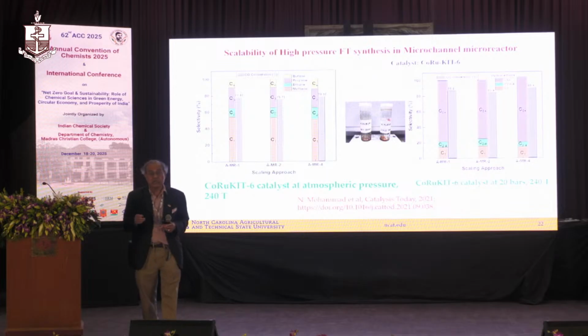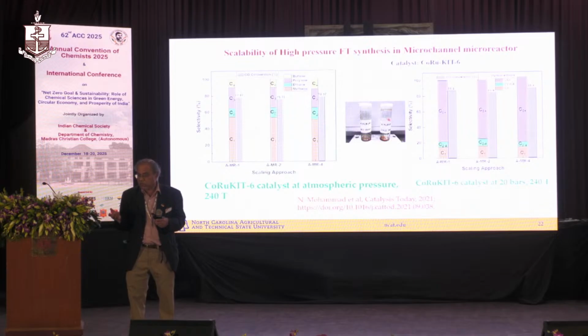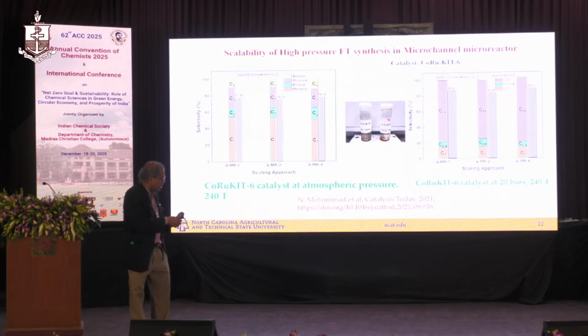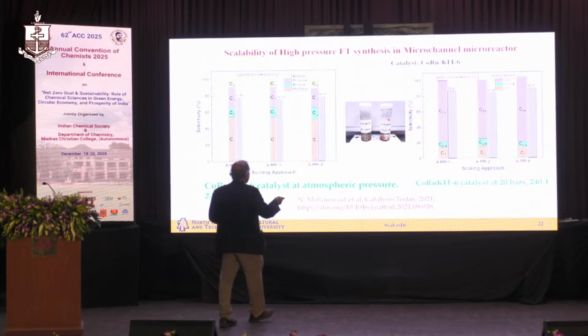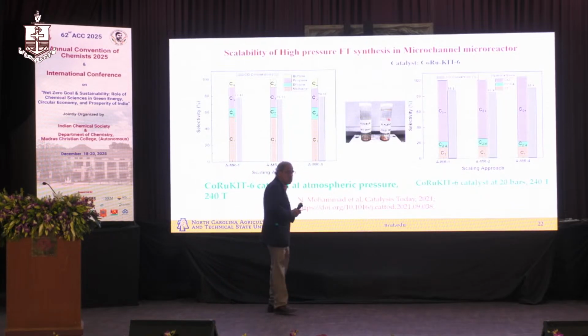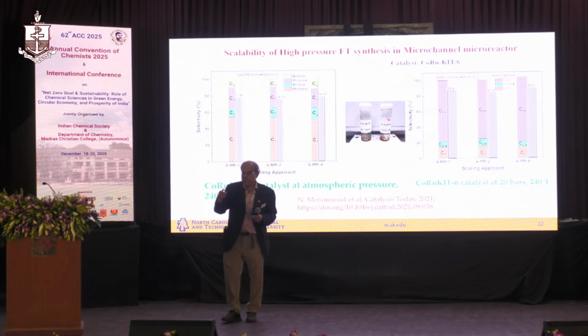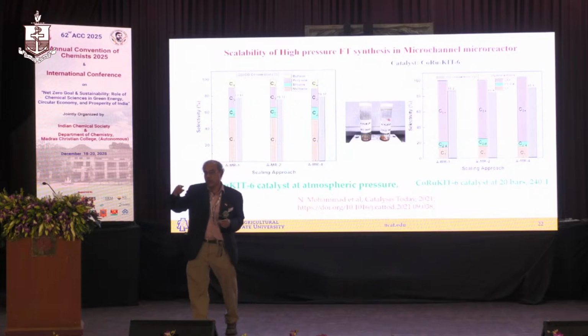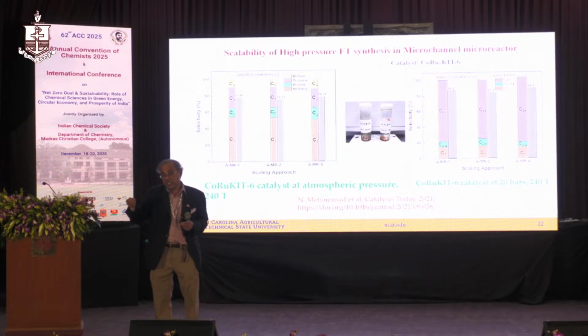Because we had never seen the liquid, because we had been running these reactions at 1 atmosphere. But the moment you go to higher pressure, this is this tiny, like a lab on a chip idea, these reactors, and we could see these liquids, and we were very excited. The reason was we were working with NC State, those who are doing the reforming of the biogas, so you get the syngas, so we could do the on-site production of liquid fuels. And we did demonstrate that we could really do it.